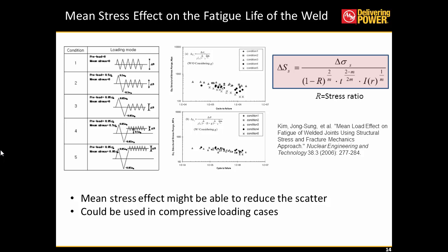Mean stress can arise due to, let's say, preload, or even due to load, or even because of the presence of residual stress, which can be considered as a mean stress effect. In this particular case, some tests were conducted and different kinds of behavior were observed. As you can see from the chart below, if you don't consider the effect of mean stress, then there is significant scatter. And if we include the mean stress term, as you can see in the right-hand side equation, we'll be able to reduce the scatter significantly.